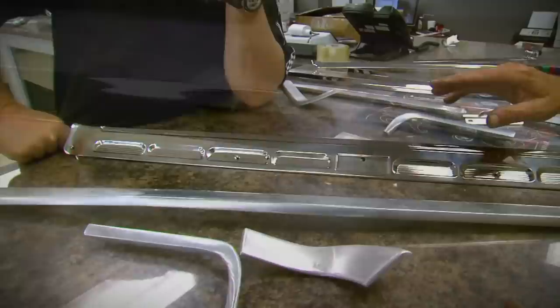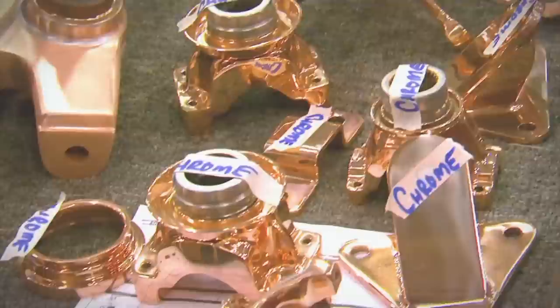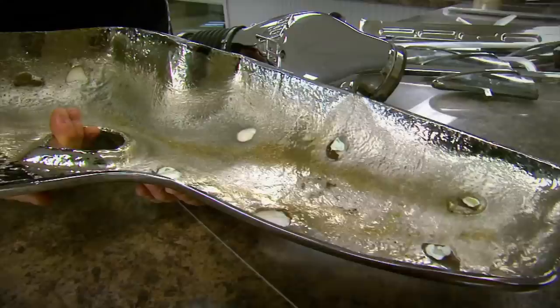The process for plating on stainless is that it initially goes through a nickel strike — a bath of hydrochloric acid and nickel chloride — and that is where the adhesion comes from. Then it goes back to copper plating. The aluminum goes through a zincate and then to copper. So now you have no excuse to have dirty, dingy, scratched-up, mismatched trim on your muscle car. In fact, the guys at Advanced Plating have even developed a way to put chrome on fiberglass and plastic.